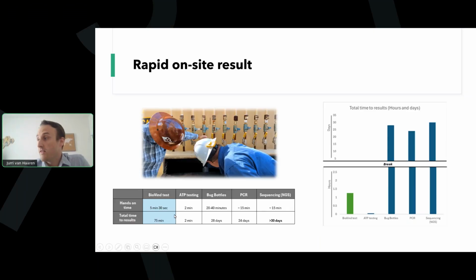When we compared this to some of the other methods out there, we saw that the only test that can outperform ours is ATP testing. ATP testing is just so easy and so simple. It's super fast, but again, doesn't give you any information. But when you compare it to bug bottles, PCR, or sequencing, you see that we are much faster and provide results within an hour and a half, whereas the other ones take several days or weeks to get your result back. So performance is looking pretty good there.